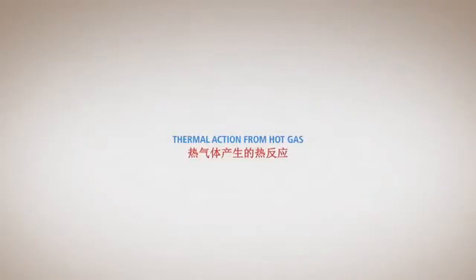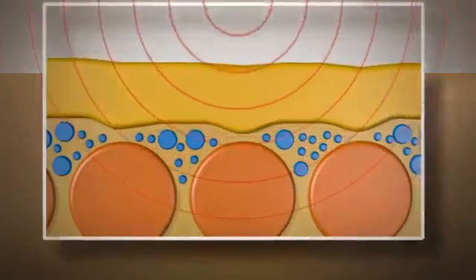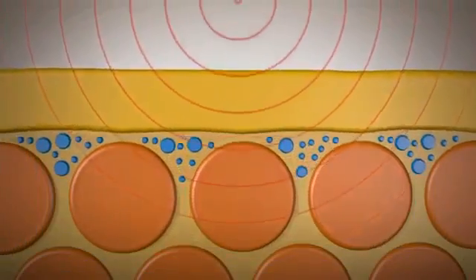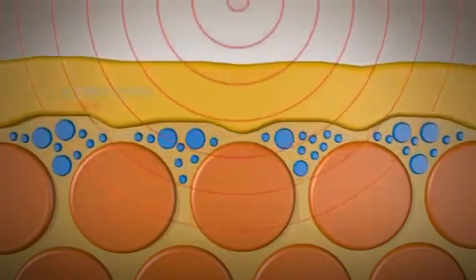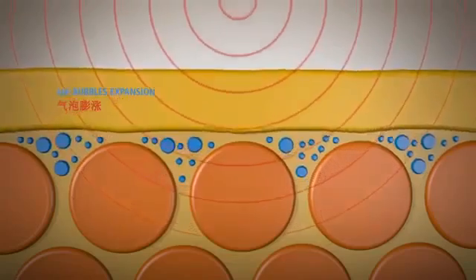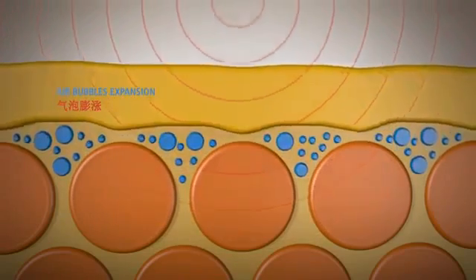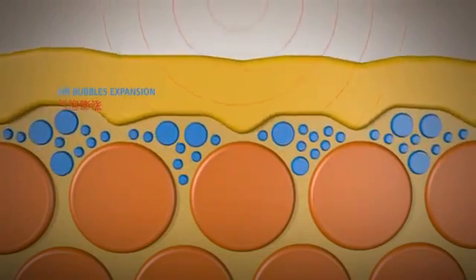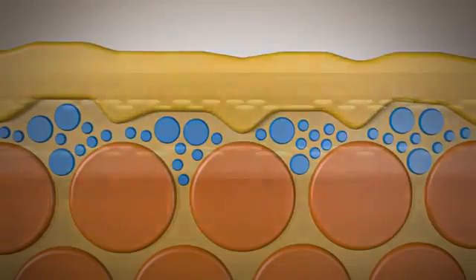Regarding thermal action from hot gas: delamination, or the separation of the glass layers which occurs following an increase in the volume of air between the various layers in the presence of heat, has been totally eliminated by using a 100% hand lay-up process and high mechanical strength materials. This makes it possible to achieve relatively slim thicknesses and layers which are far more compact, as the laminate is made up of uniform layers.